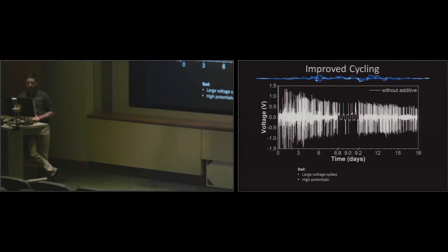So this is what it looks like with a regular system if you cycle and you have dendrites present. If you think this looks pretty messy and unstable, it's because it is. So if we zoom in here, you can see that it's not a very flat potential like we would want, and there's all these sort of large spikes which are indicative of these dendrites growing and like little micro shorts basically happening. So what my research involved was finding an additive to add to the electrolyte to improve the performance.